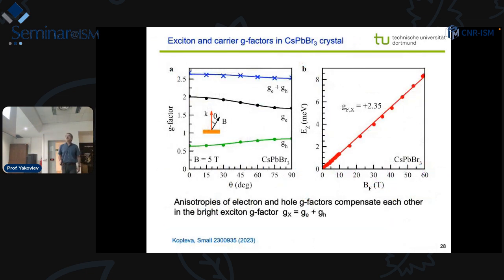So this is an example when we measure anisotropy. This is a cesium lead bromide with the c-axis. In these directions, we can apply the magnetic field parallel to it, perpendicular to it, or at some angles. And we observe that the electron g-factor decreases its value, the hole g-factor increases its value. What is interesting is that the exciton g-factor, which is the sum of the electron and the hole, becomes nearly isotropic. And this is kind of a rule of thumb for the perovskites.